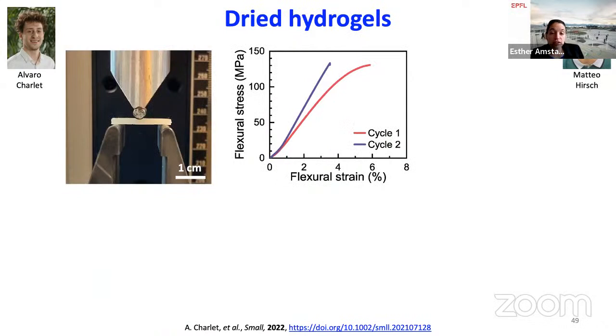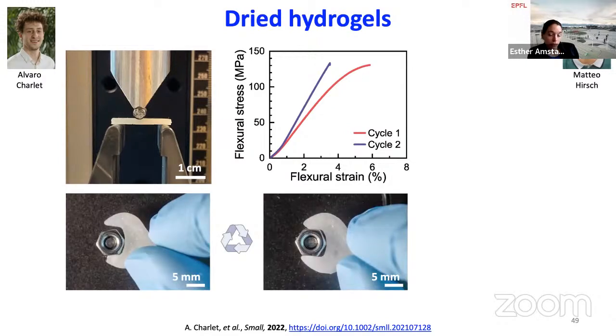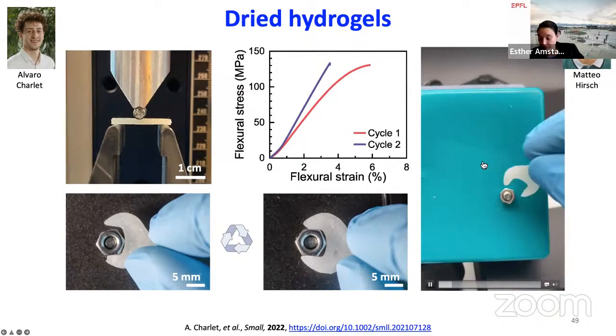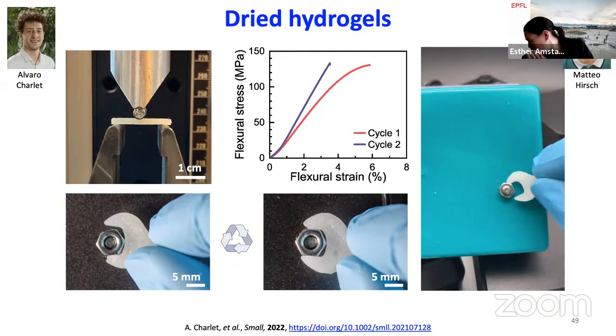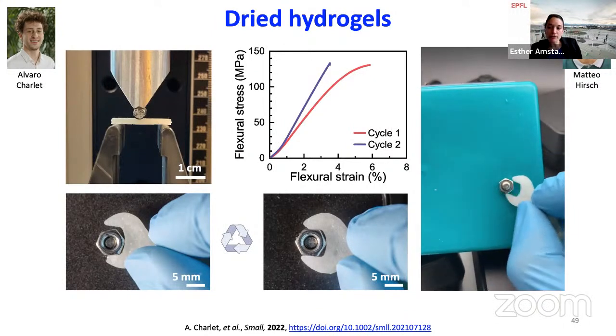Now, hydrogels are inherently limited in terms of stiffness and strength. And just to demonstrate feasibility, we showed that if you dry these hydrogels to get a dried polymer, you actually increase the stiffness by a lot, and that by itself is not very surprising. But what was nice to show is that even after drying, we can then recycle them within a couple of hours without compromising the mechanical properties of these materials. And just to show a full proof of principle, my PhD students cast a wrench with the wrong size dimensions. They recycled it within a couple of hours, cast a new one that was able to then help tighten a bolt made out of metal. Showing that actually the mechanical properties of these materials are pretty good.